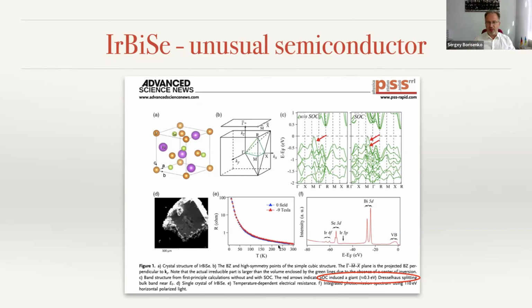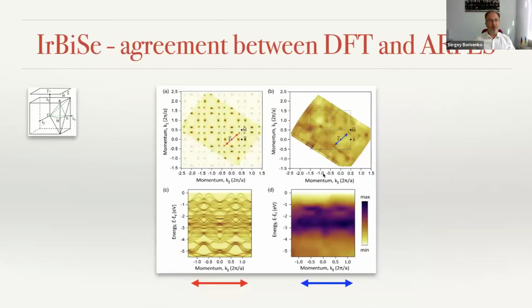So the resistivity, as you see, does not depend on magnetic field a lot, and the samples were very nicely characterized in Princeton. The ARPES data from semiconductors are usually not very spectacular because there is an energy gap, and in this particular case, the density at the Fermi level was relatively not very low, let's say, but nevertheless, one could still find the parallels with the band structure calculations. One could see that there are spots, what we call the remnant Fermi surfaces, very nicely reproduced in a large area map. And even the band structure was looking approximately the same, but similar.